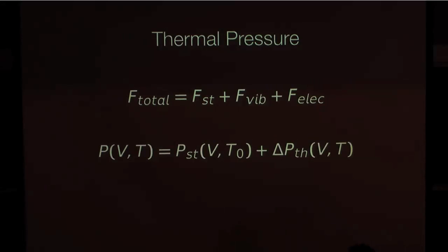I think it's worth mentioning that the thermal part, especially if you take the electron out, solely comes from the asymmetry in the interaction potential of atoms. Not solely. It could come from the asymmetry of the interatomic potential function, particularly if you go very near to the melting point. But fortunately, bridgmanite has a really high melting point, way above the geotherm, right? So that anharmonic term is normally assumed to be small, so you don't have to worry about it.